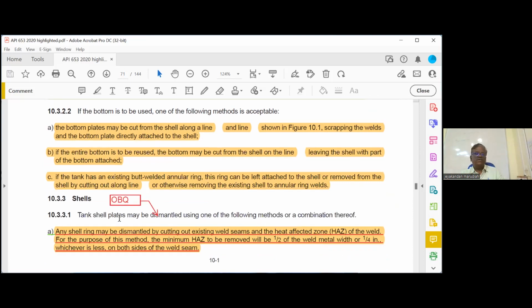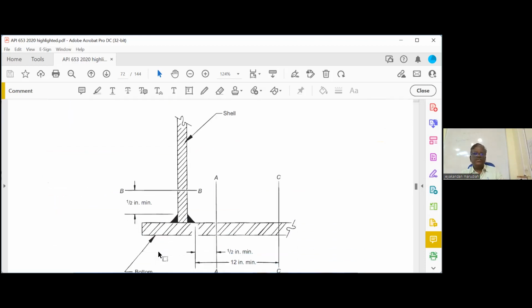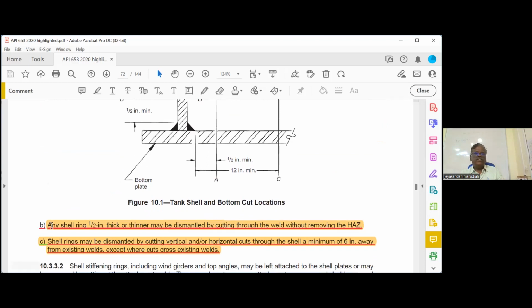Shell. Come to the shell. Any shell ring may be dismantled by cutting out the existing weld seams and the heat affected zone of the weld. For the purpose of this method, the minimum heat affected zone to be removed will be half of the weld width or 1/4 inch, whichever is less. So we will take only 1/4 inch, 6 mm as a heat affected zone for this purpose. The next page, highlight the B. Any shell ring half inch thick or thinner may be dismantled by cutting through the weld without removing the HAZ. So no need to remove the heat affected zone when the thickness is half inch thick or thinner.